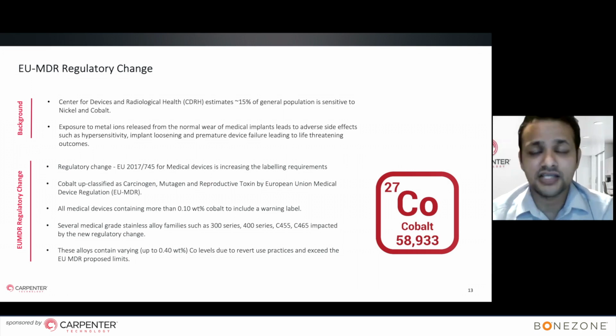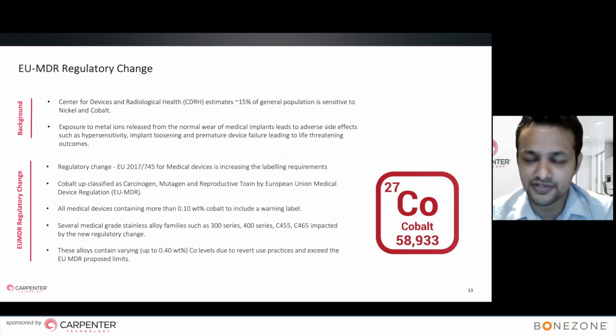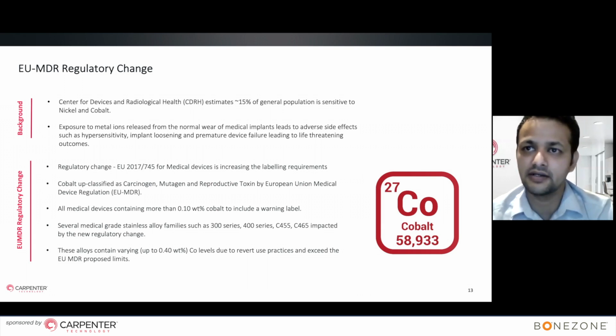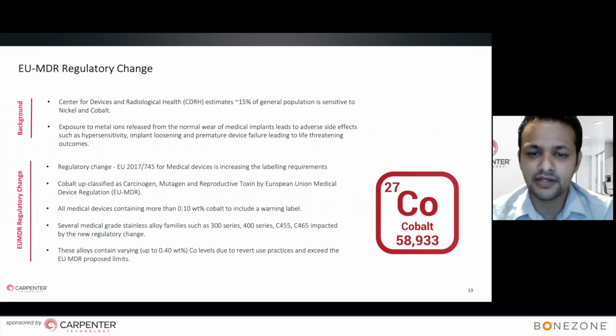which has been shown and reported to lead to severe complications, implant loosening, metal allergies, hypersensitivity reactions, and additional complications that require revision surgeries. So there was this whole concern about cobalt being leached out and elemental cobalt causing significant complications, which led to more scrutiny with respect to cobalt content in medical devices.